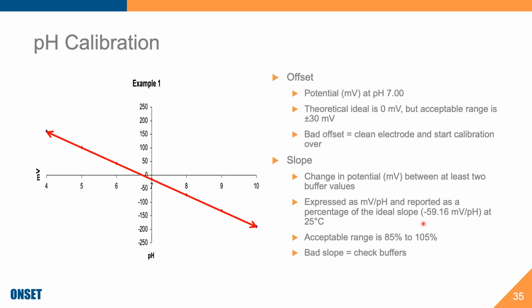So if you can remember back to that Nernst equation, that crazy equation that looks at potentials and constants and gas constants and so on, you'll note that at pH 7, at room temperature, the slope of the calibration curve will be negative 59.16. And so any slope that we get after that when we're calibrating, because the slope will change, we take that value and divide it by negative 59.16 at 25 degrees C. And the acceptable range for that is between 85% and 105%.